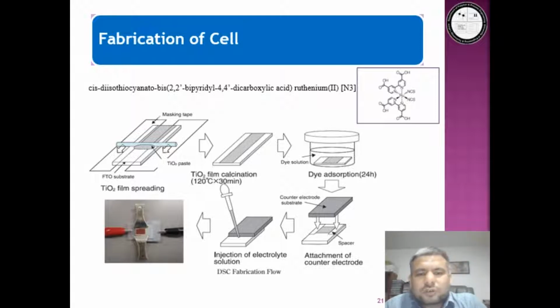counter electrode. After fabrication of both electrodes, the prepared solid state electrolytes or polymer gel electrolytes were deposited on the photoanode. Then it was heated for 50 to 60 minutes at 50 centigrade. And both electrodes were then joined together by super glue or epoxy based adhesive. So this is the fabrication of the solar cell.